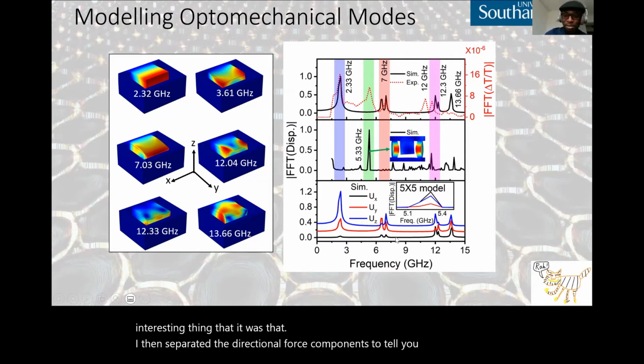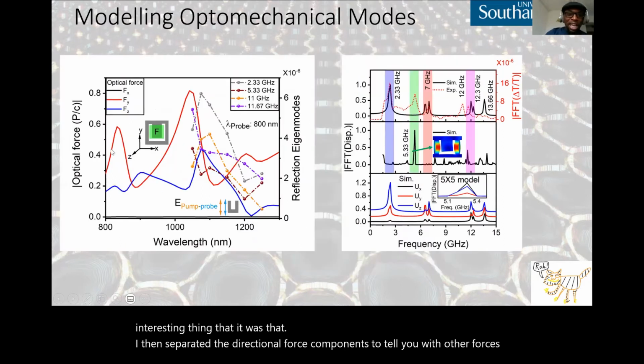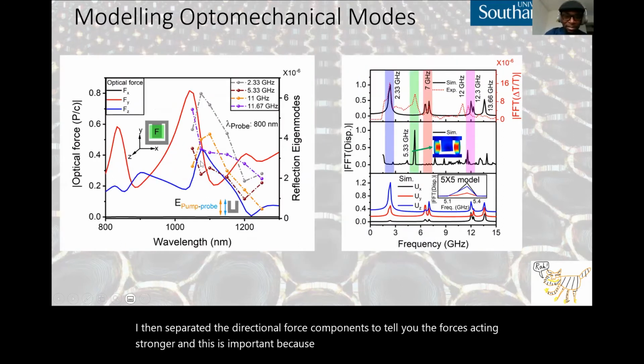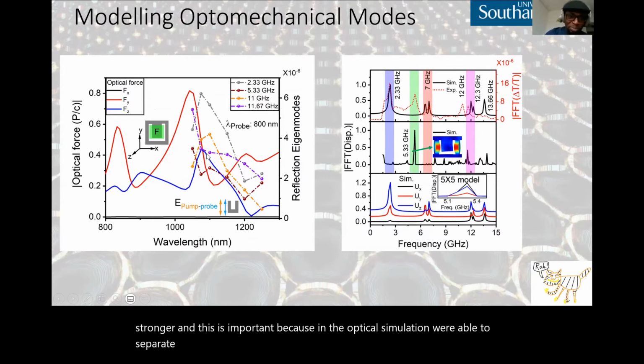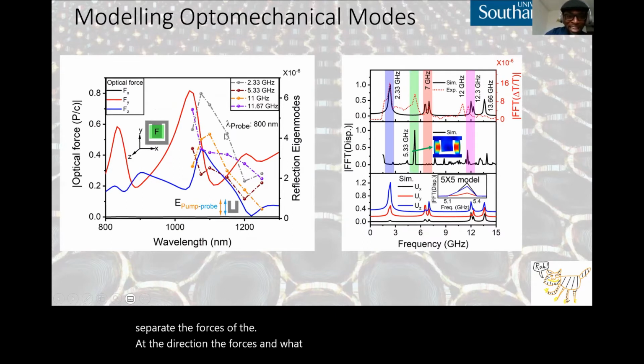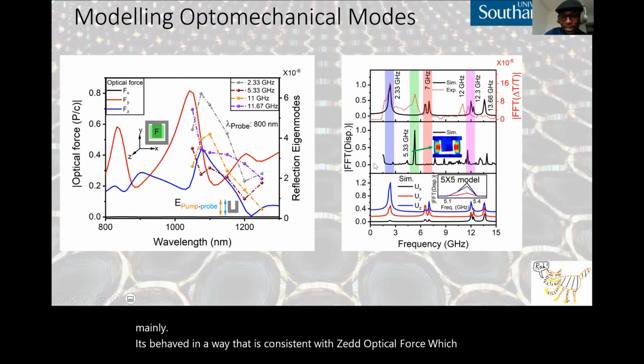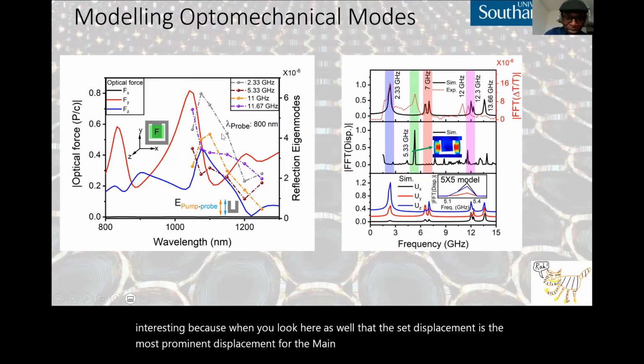And this is important because in the optical simulation, we're able to separate the forces by direction. And what we found was that the main mode behaved in a way that is consistent with the Z optical force, which is quite interesting, because when you look here as well, the Z displacement is the most prominent displacement for the main mode. And this was also the same for the mode at 11 gigahertz, which is somewhere around here.